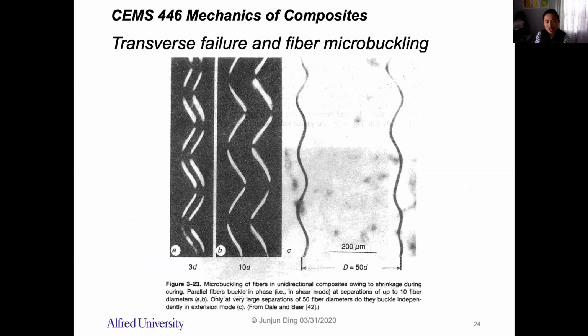So this is the experimental result. I think this is the SEM image for the two buckling mode, right? So in the A and B case, right? So the distance between those two fibers is around 3D. D is the diameter of the fiber, okay? And the B case distance is 10D. So there's still relatively small distance compared to the diameter of the fiber.